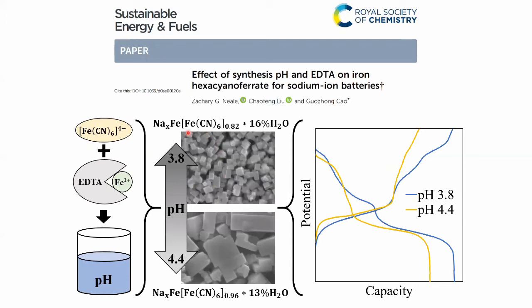So what I want to look for is the number of vacancies of this iron cyanide precursor that are in my samples at different pH. Typically, in that last example I just gave, we looked at the number of vacancies through a chemical analysis. We looked at ICP, comparing the ratio of lead to iron, for example. But in this case, we have two chemical species that are both iron, so you can't do any chemical analysis to show you which iron is missing, right? So this is where Mossbauer has an advantage, is that this iron is chemically different than this other iron. So this iron is coordinated to six carbons of the cyanide, where this other iron is coordinated to six nitrogens of the cyanide, and that changes the chemistry of that iron.